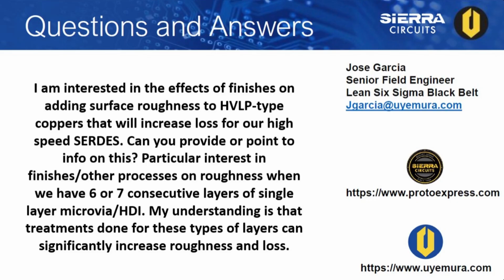Again, roughness of copper is a major contributor to signal loss. In fact, it would have a much more significant impact than the final finish on insertion loss. So when you get above 40 gig, you just got to get everything right. You got to have the right materials, you got to have non-rough copper, and you have to choose the right final finish. Okay, so it's kind of all three things. Every presentation I've seen on this particular subject says the same thing, and that's that above 40 gig, you need everything right in order to deliver the performance that they're looking for.